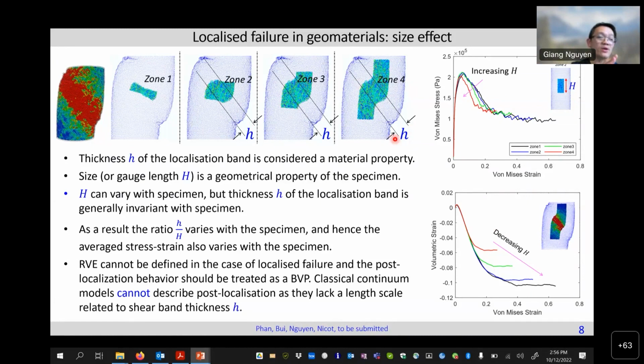So that length h is somehow the material property, at least in loose sand. It's not absolutely correct, but it's a material property. So the ratio here between the size of the band and the gauge length is creating something called a size effect here, because we are varying h, but the material in this case doesn't allow us to vary the size, the thickness of the band, because that belongs to the material. Okay, so this thing is the size effect that we have to end up with, and in this case we cannot define the stress-strain relationship in a normal way. Okay, everything is broken down in this case, so we won't go to the details in this case,